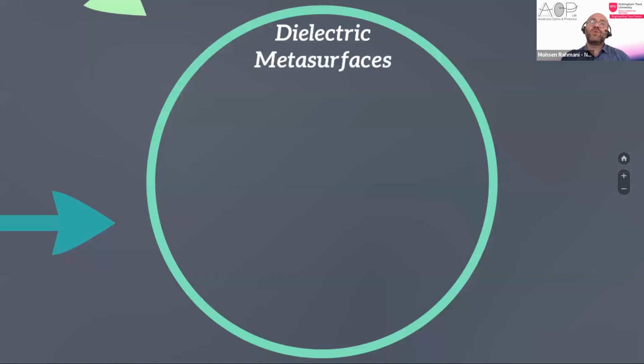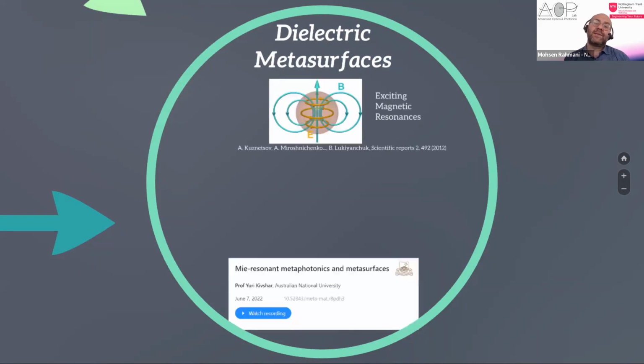So because of those issues, mostly loss issue and low heat resistance, people migrated to dielectric metasurfaces. Dielectric metasurfaces are based on dielectric and semiconductor, or in general, high refractive index nanoparticles. The good thing about them is that they can have the field inside the nanoparticles, unlike the plasmonic nanostructures. Therefore, you get the magnetic field also involved and generated by these dielectric nanoparticles.